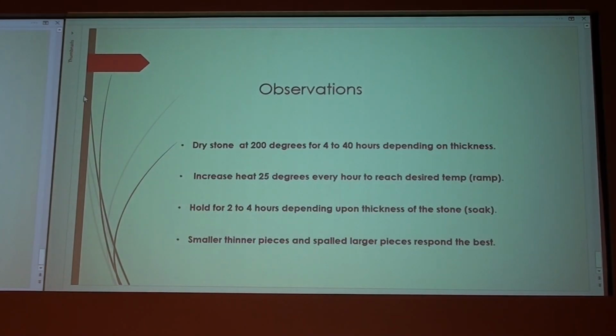So some of the observations that I came up with: dry the stone at 200 degrees from 4 to 40 hours, depending on thickness. And I did find that increasing heat 25 degrees every hour to reach the desired temp was better. Otherwise, I jumped 50 degrees. And some people jump 100 degrees. I don't know how that would work. Hold for 2 to 4 hours, depending on thickness of the stone. And smaller, thinner pieces, and spalled larger pieces respond best, which makes sense. And that's it.